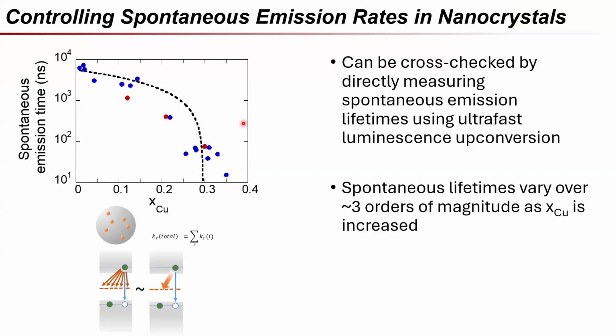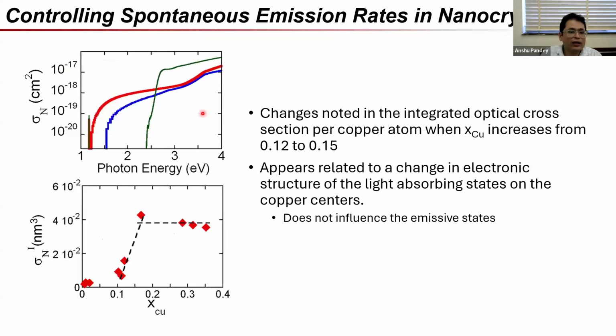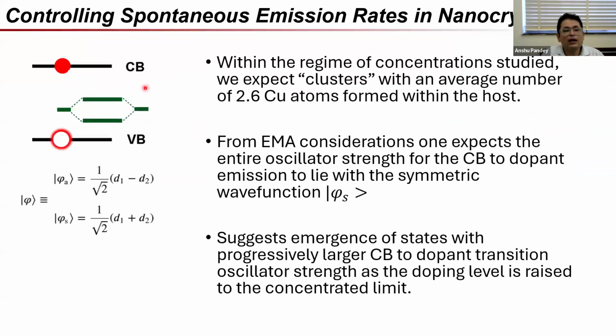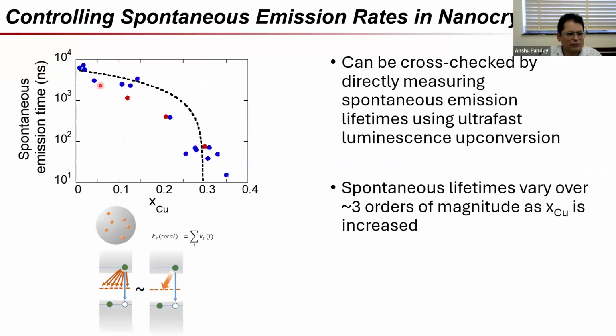Generally, if a species is paramagnetic, they don't show fluorescence. I don't know about this nano. They show. In the copper case, they are very fluorescent. So copper itself, okay, I understand, it's coming from an inorganic chemistry viewpoint. Yes, copper itself is not fluorescent. The precise thing which is happening is perhaps best shown in this diagram. The conduction band electron falls into copper as the first step, turning it from D9 presumably to D10, and then it relaxes thermally back to the ground state. But this initial fall is what is giving rise to the luminescence.